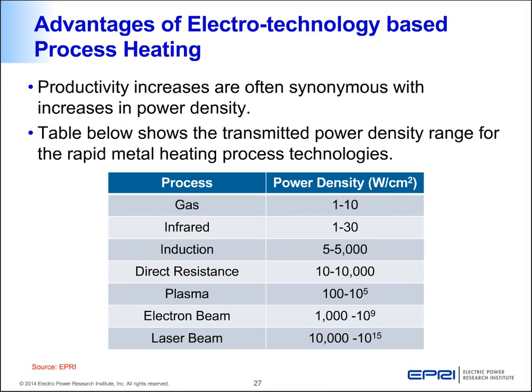The power density chart shows why infrared is very effective. As opposed to a natural gas based system, infrared could have a very high power density, up to 30 watts per square centimeter or 300 kilowatts per square meter. That's the reason why it can effectively transfer the heat to the object and increase the speed of the production line.